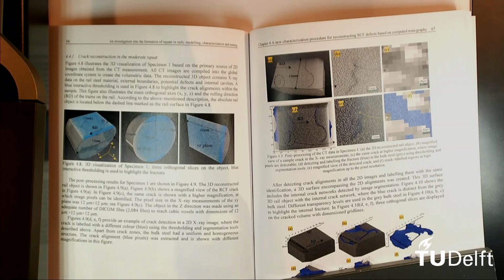It has to do with the detectability of around 12 micrometer. And of course, if you consider higher detectability, then you don't see much difference in the results, at least for the samples that I studied. I also had the results for higher detectability, but you don't see much differences. At this level of detectability, you are able to see the cracks only by dark regions.